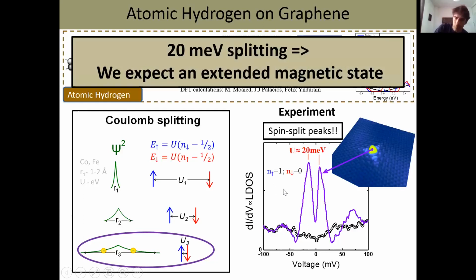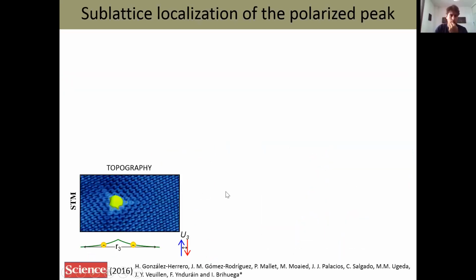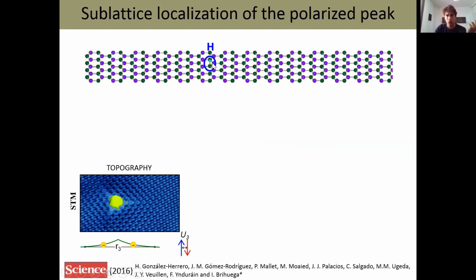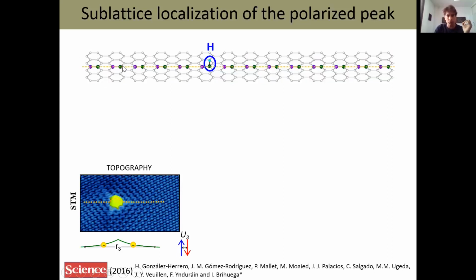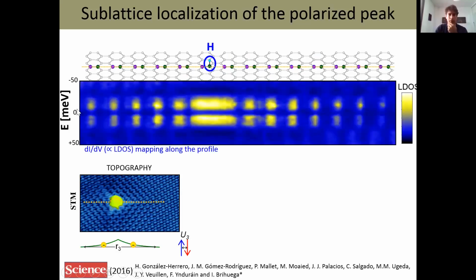Okay? So if what I'm telling you is true, what we expect to have is a very extended magnetic state. And that's something we are very good at probing in STM. So that's the adsorption of a hydrogen atom on graphene, and we can know with atomic precision where the hydrogen atom is sitting. You have these 3 legs, you make lines, and the position where they cross tells you where the hydrogen atom is. So now instead of just making an IV curve on top of the hydrogen atom, we make a series of IV curves along this line. So what we will be doing is probing the density of states of graphene along this line. When we do such an experiment, that's the result we get.